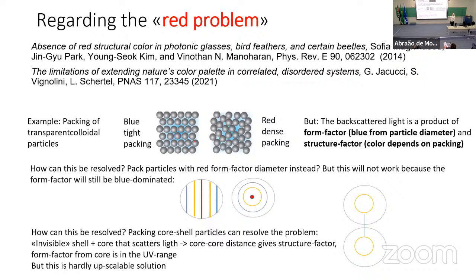So each particle gives a form factor to the scattering, and the packing gives a structure factor. Imagine that these particles have a diameter corresponding to a blue color. Then the form factor is blue. If you pack them very densely together, you also get a blue structure factor. If you take these blue particles and pack them loosely, you get a red structure factor, because the distances between the particles increase.